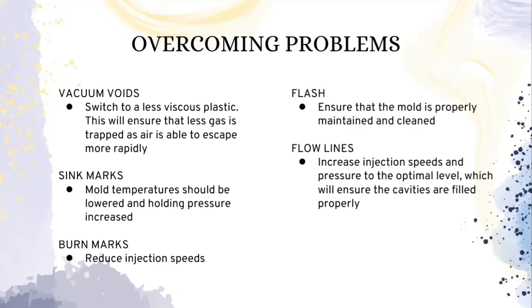To overcome flash, we can ensure that the mold is properly maintained and clean. For the problem of flow lines, we can increase the injection speed and pressure to the optimal level, which will ensure the cavities are filled properly.